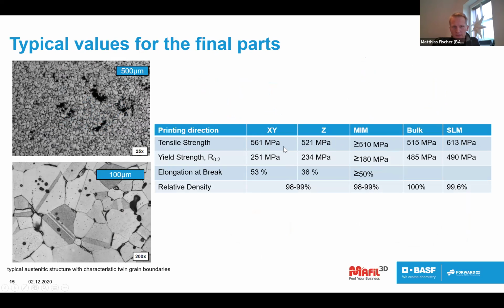So here I'm already coming to my last slide. When you have the metal part, you may have the question: what can I expect here? Which kind of mechanical properties can I expect? And of course, we also have a difference here between the flat and the upright build orientation. In the Z direction, we are limited by the anisotropic behavior of the filament printing process, but in general, you still have a tensile strength which is at least almost in the area of the XY direction.